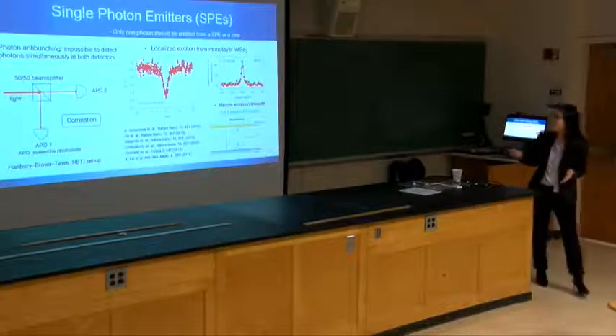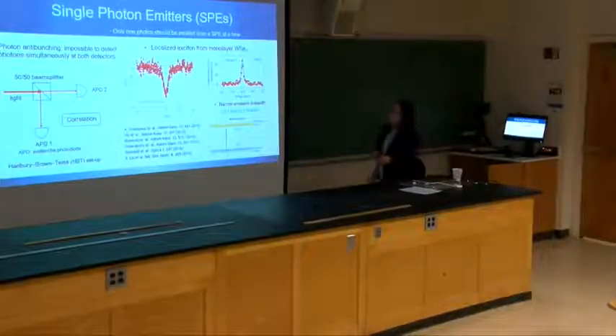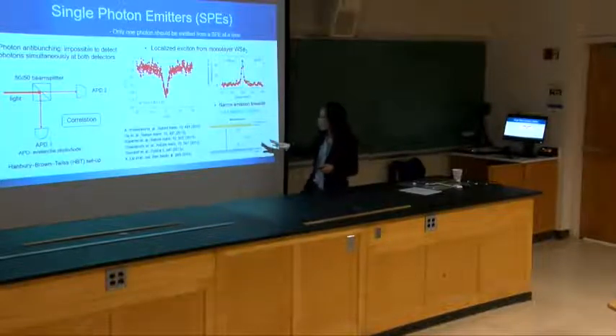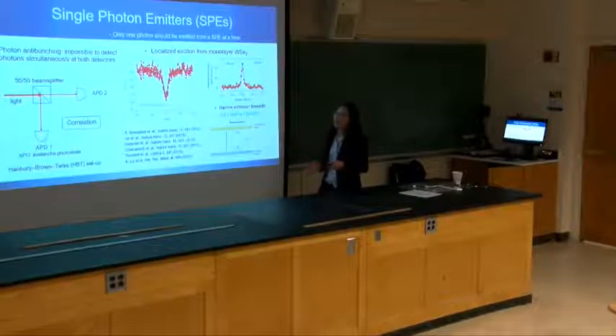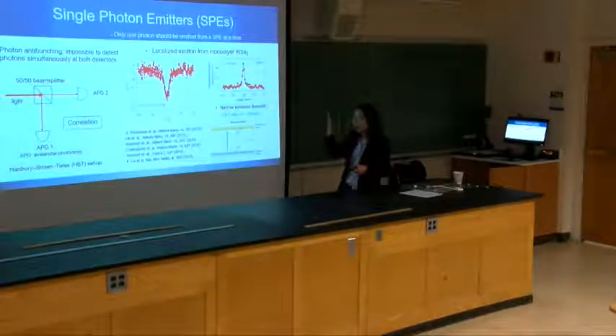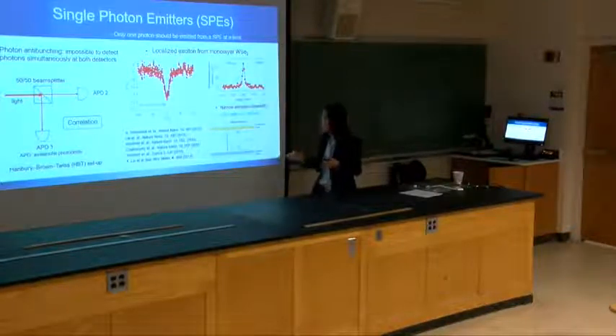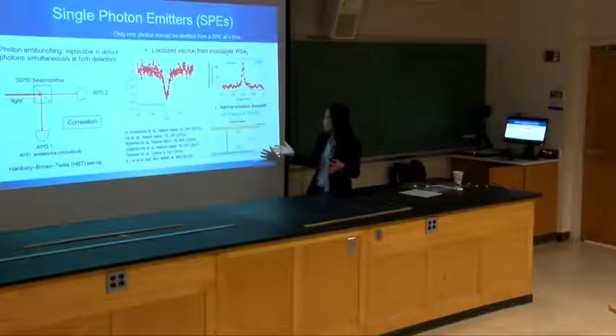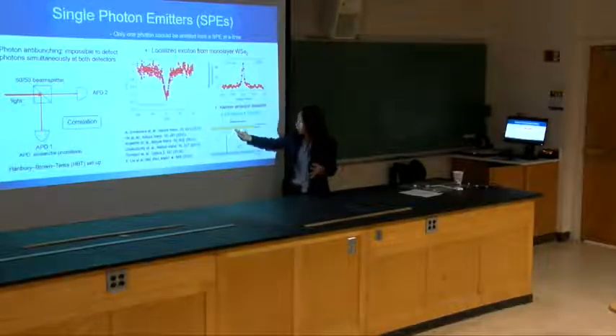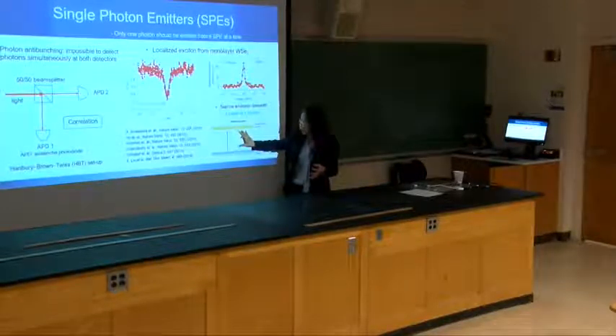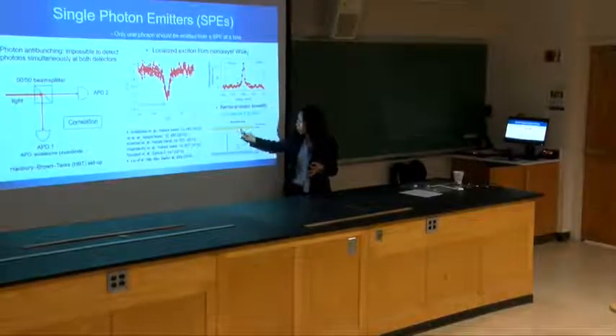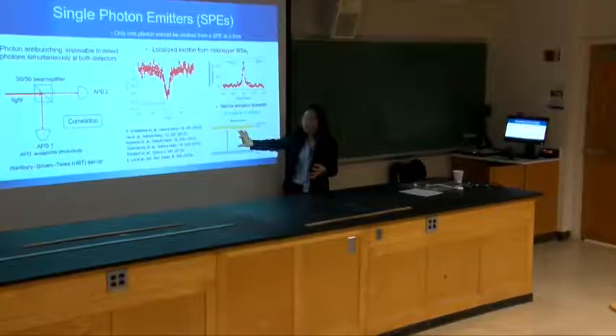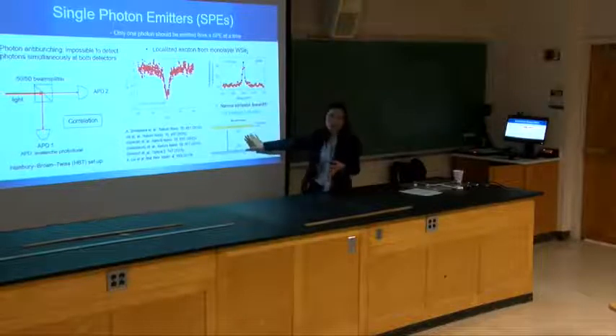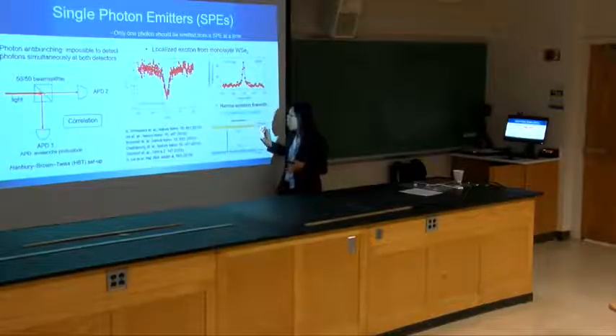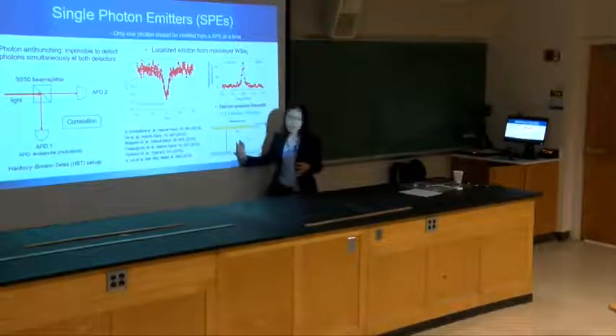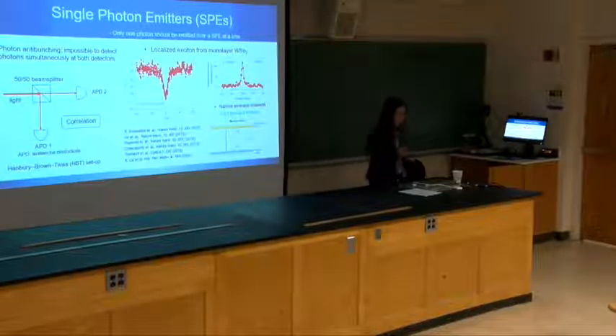Here I need to clarify the difference between a localized exciton and a delocalized exciton. The exact origin of the single photon emitter in layer materials, or in tungsten diselenide, is still an open question. But basically, we consider it an exciton localized by a shallow trap, like here. So only at a certain location does it emit. We consider that the exciton emits from this localized potential, and that's the localized exciton. For the delocalized exciton, one can expect to see it anywhere in the sample, as long as you excite it. So that's the difference here.